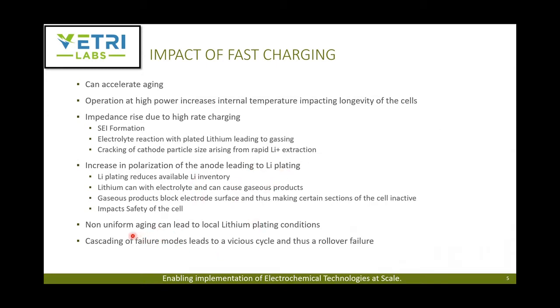And again, the non-uniform plating can lead to local lithium plating. So it doesn't have to be the entire anode that's plated with lithium. Even the local lithium can lead to these regions here, these reactions. As we can see, one can lead to the other, and then lead to a vicious cycle, and thus a rollover failure or an exponential failure rather than a linear failure.